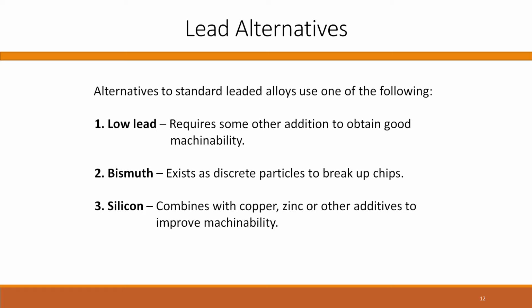The other attempt to get a highly machinable alloy is silicon, either in combination with copper and zinc or in combination with other elements from the periodic table like manganese, for example. In the proper combinations it can give you a very machinable alloy, but it's not soft and smeary like lead, and so that can be difficult on tooling unless you make the right changes to your tooling and your machining parameters so that it gives you the best machinability.